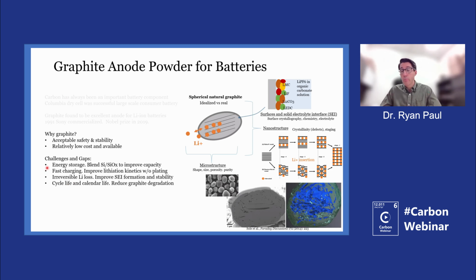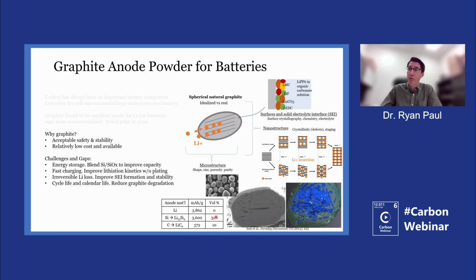So although this is the dominant material, it's still not perfect, and there's still energy storage gaps. So the trend today for electric vehicle manufacturers is to blend in silicon to improve the capacity. This is because silicon has a much larger reversible capacity than just pure carbon from a battery energy storage perspective. But on the other hand, you have with the lithiated silicon a much larger volume expansion, which means the tendency to crack and to spall. And so balancing that is a bit of a challenge.